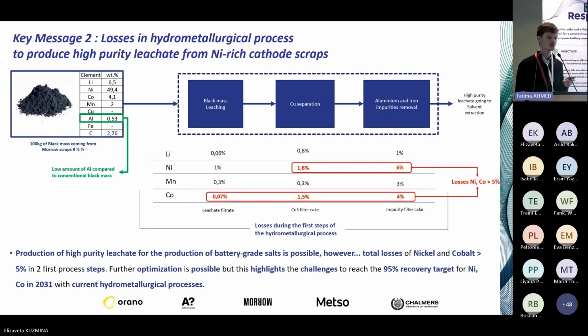So in terms of organization for this hydrometallurgical part, all the operating conditions have been determined by Aalto University in Finland and Chalmers University. And then the company Metso has a pilot line for hydrometallurgical treatment in Finland for the 3 first process steps of the hydrometallurgical treatment. And a pilot test was performed in Finland for these 3 process steps: the leaching, the copper separation, and the aluminum and iron impurity removal. The input material for this test was 100 kilo of black mass that was produced by Orano.